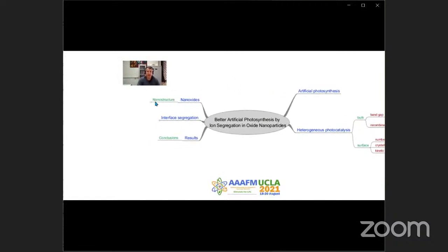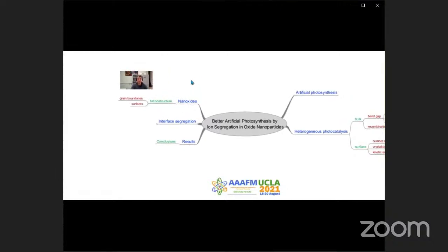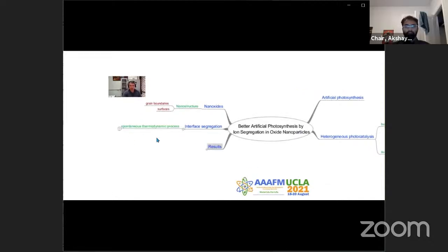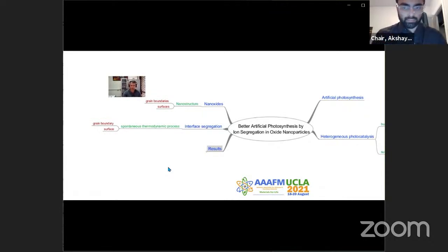These nano-oxides have nanostructure. This nanostructure has two main parts: the grain boundaries and surfaces. Grain boundaries are all interfaces between solids, and surfaces are the interface between a solid and a gas, or a solid and a liquid. The interface segregation is a spontaneous thermodynamic process for both grain boundaries and surfaces, and it's a very important phenomenon that changes all surface or interface properties, the stability of particles, the reactivity of surfaces and interfaces, and the electrical conductivity.